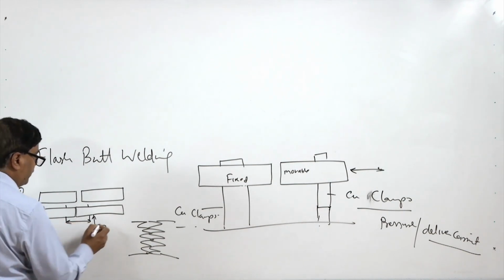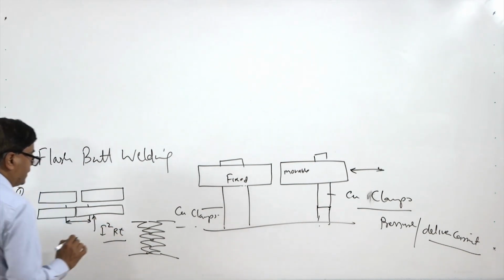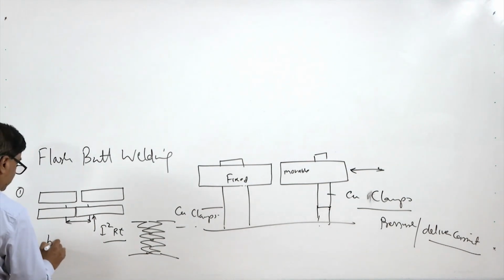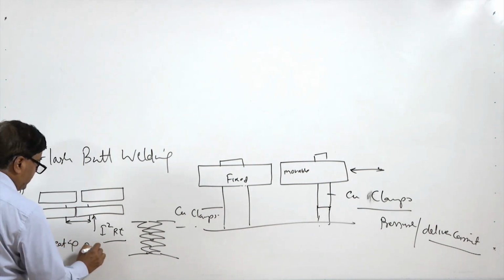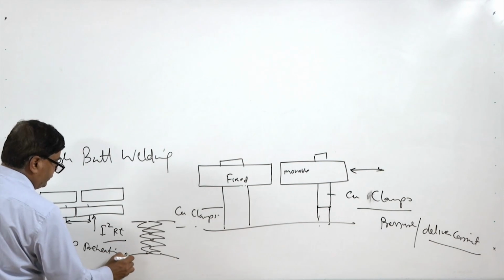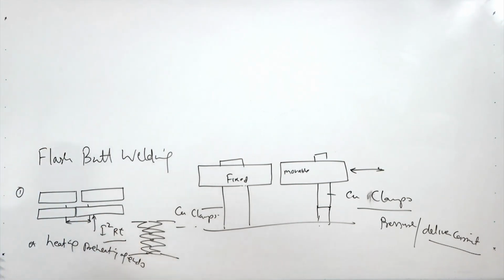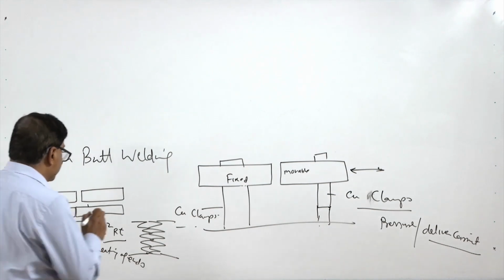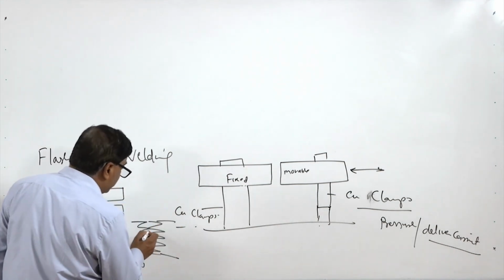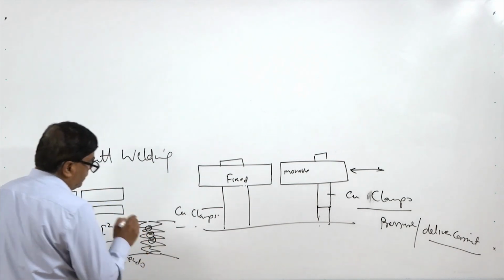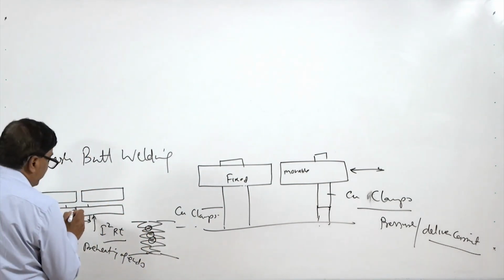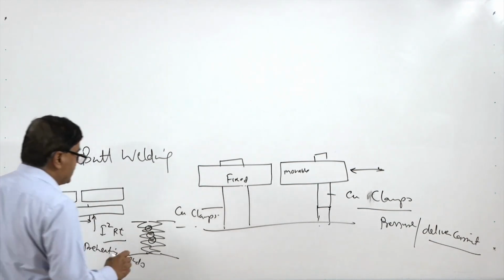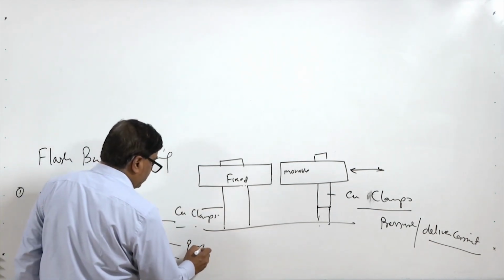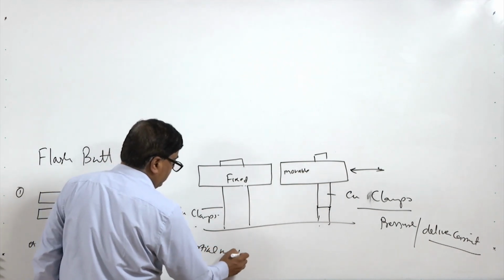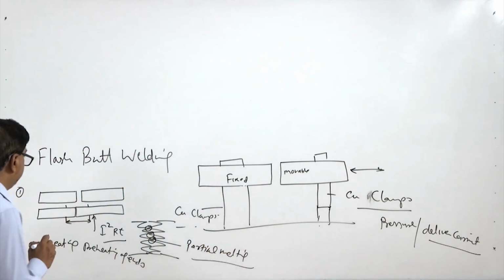So, the flow of heavy current causes I square R T heating to take place. During this heating, the ends being joined are preheated. At the same time, since the contact is very localized, excessive heating at very localized points can take place, which can cause partial melting of the peaks.